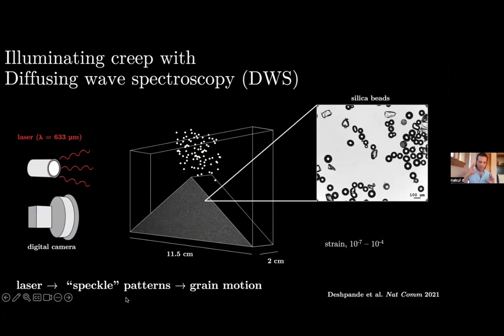The basic idea of this technique, diffusing wave spectroscopy, is that you have a laser, and this laser creates an interference pattern called a speckle pattern. When grains move, it changes the speckle pattern, and that allows us to extract the grain motions. The grain motions that we extract are strains. They're volumetric strains on the order of 10^-7 to 10^-4. So these are really, really small motions. It's a quite sensitive technique.